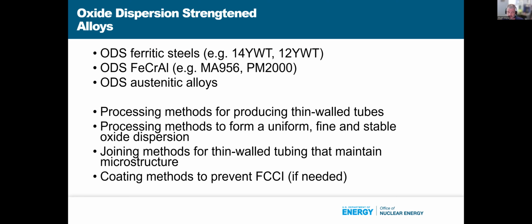These are 5 to 10 or even larger nanometer oxides, and so not as high a density as what you can get in the 14YWT. So that really makes it not as advantageous from a radiation tolerance standpoint. So can we address that to make ODS FeCrAl, but with the fine oxide dispersion? And also oxide dispersion strengthening to austenitic alloys.